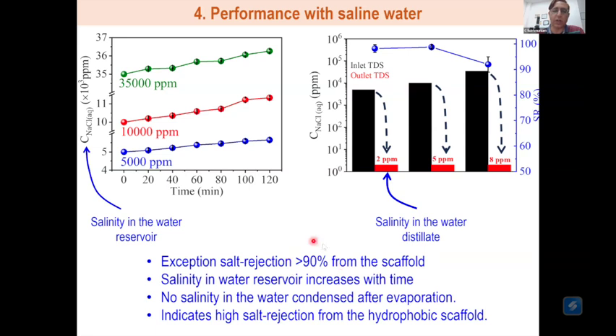We can get as high as 90% salt rejection from this interfacial coating, which we have also established through detailed COMSOL simulations, where we see that the heat is basically restricted only to this interface and not into the bulk water. So we are selectively heating the water at the tri-interface where light meets NCF meets water. So this combination of light, NCF, and water is very powerful, because light is able to interact with NCF.